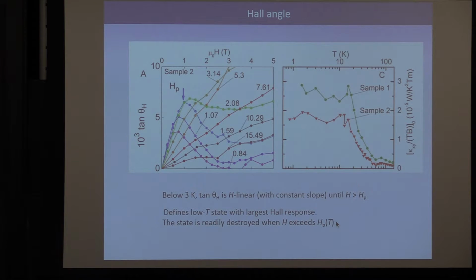So we detect a phase at very low temperatures that has a lot of spin excitation, and they have this interesting novel property that they have a thermal Hall effect. And it's a very fragile excitation. When the system orders in a strong field at 2 Tesla, it goes away. Right? So in fact, you would have thought that, well, when it orders, you should have a lot of spin waves, right? But the spin waves do not add to the thermal Hall effect. In fact, they basically remove this interesting excitation.